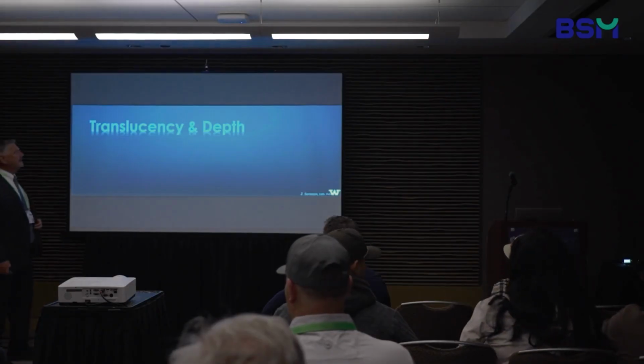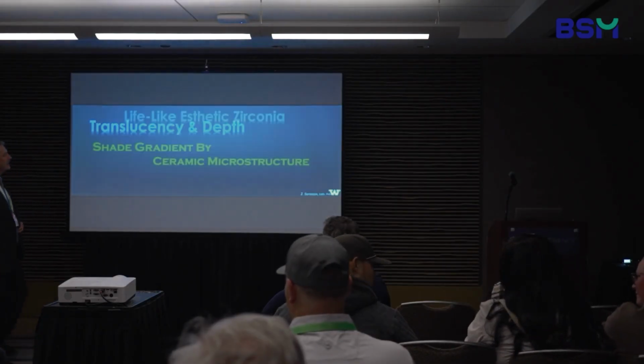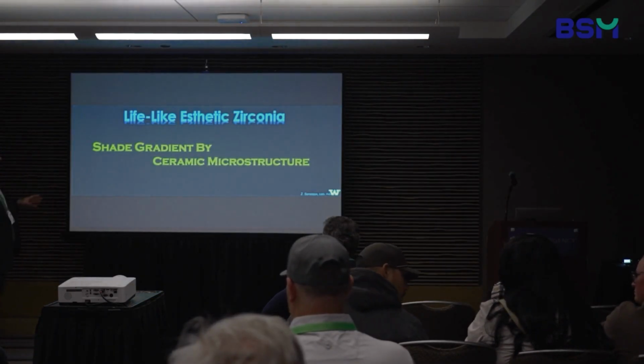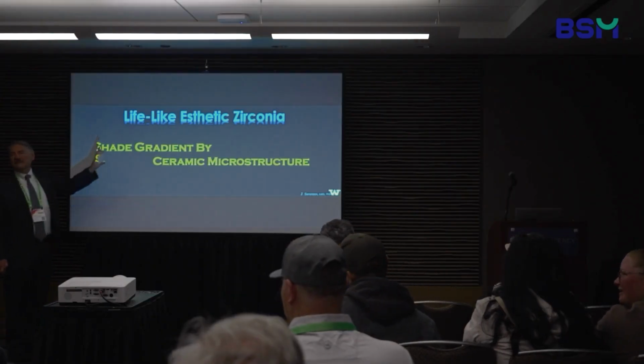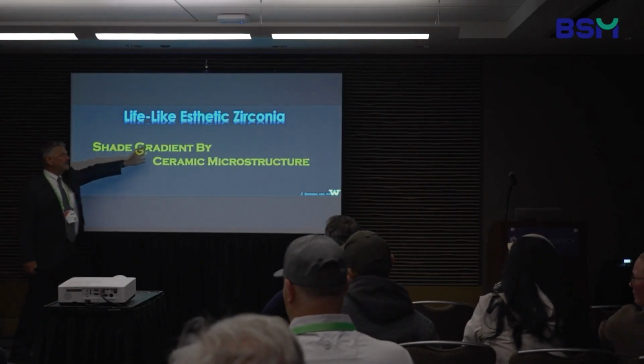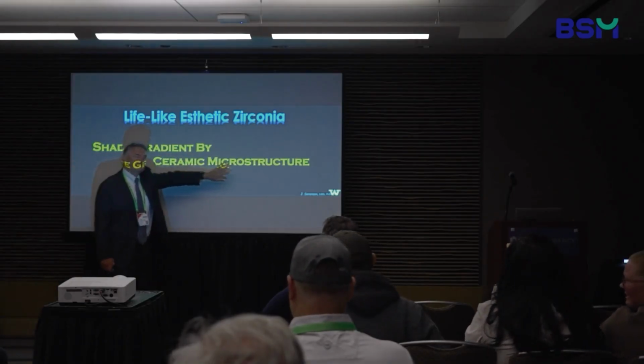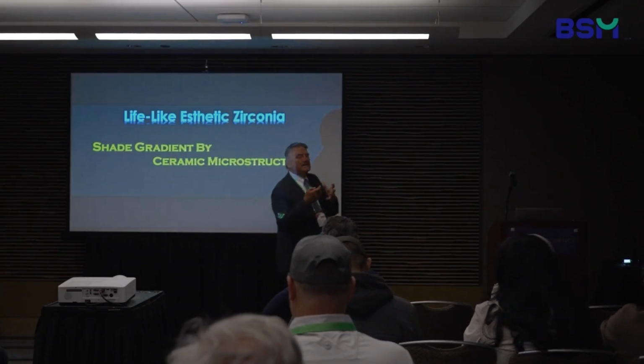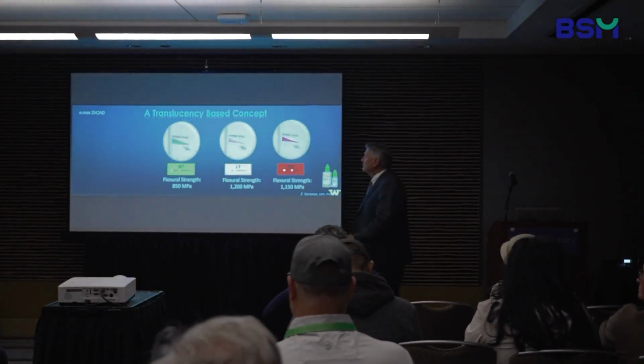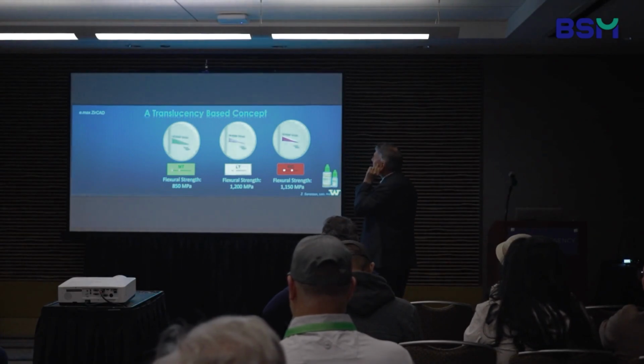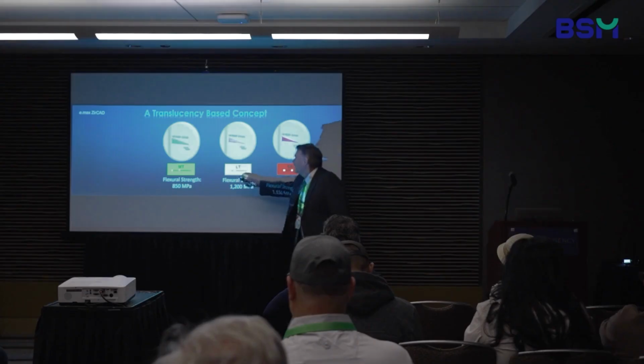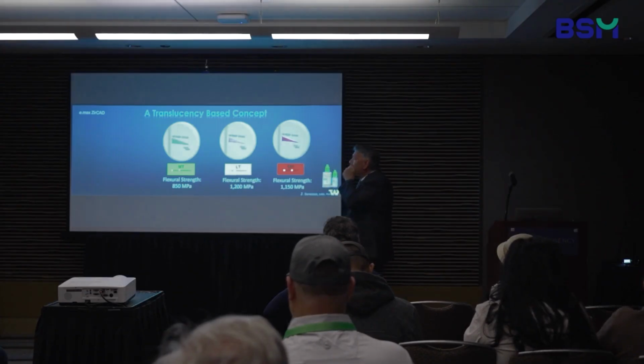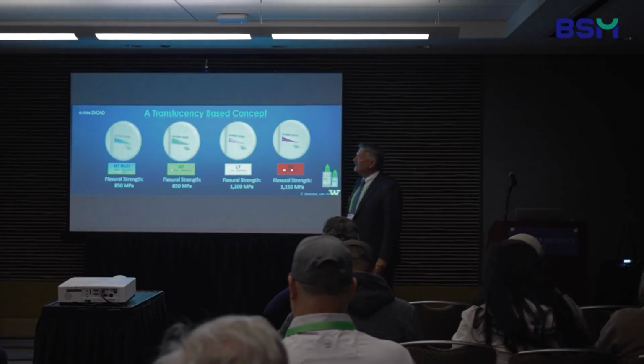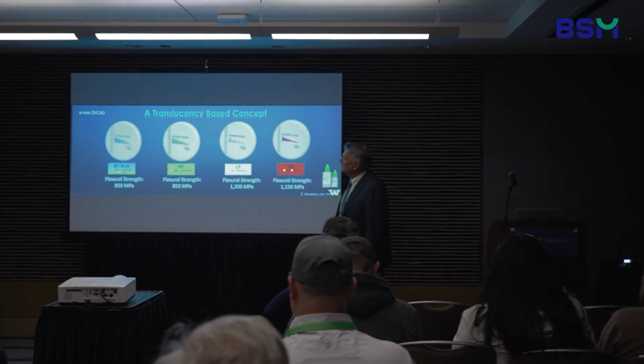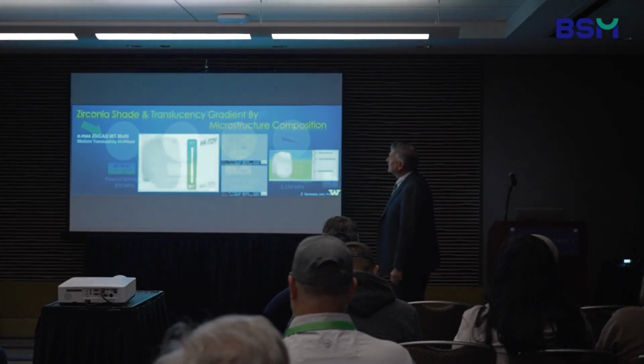But we'd still like to have more translucency, more depth in our actual materials, and so a better way to create an aesthetic restoration is to have a gradient of ceramic microstructure. So now we're going to have something that looks more like the natural tooth. Ivoclar was one of the first ones to come out with this. They had their different translucency materials, but they then came out with the multi-material, which had a flexural strength of about 850 megapascals. So pretty good for that.